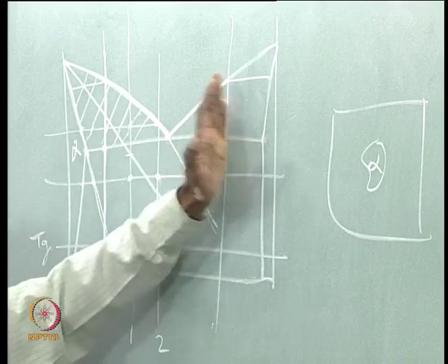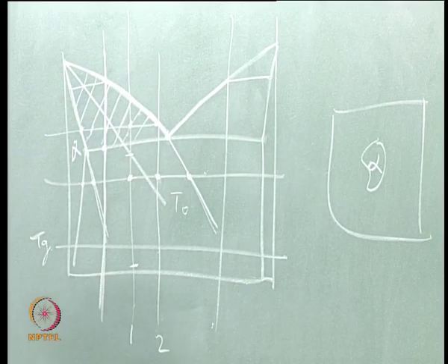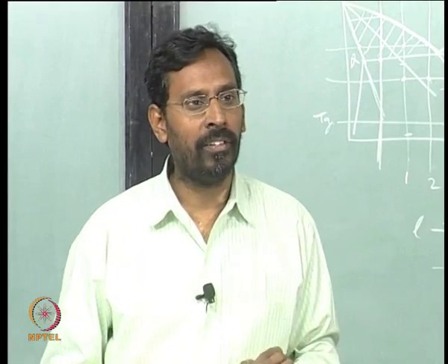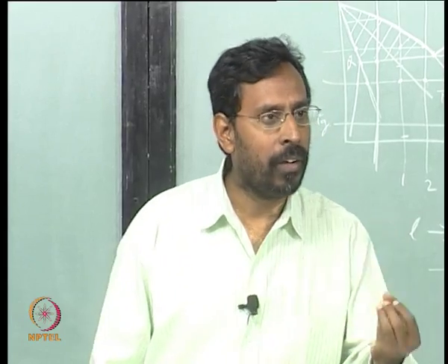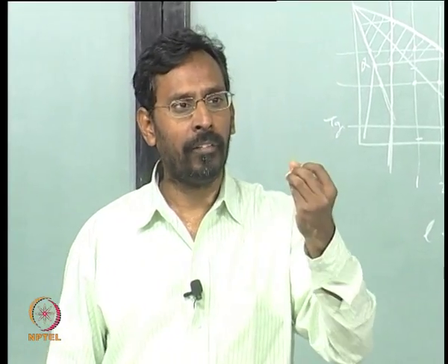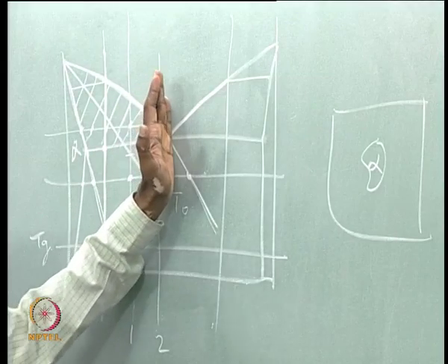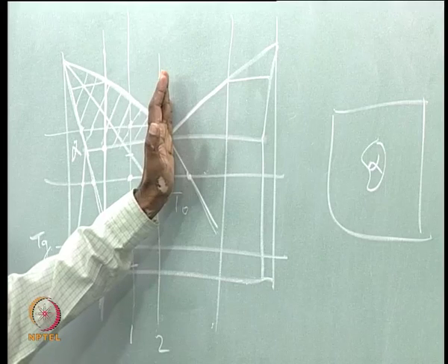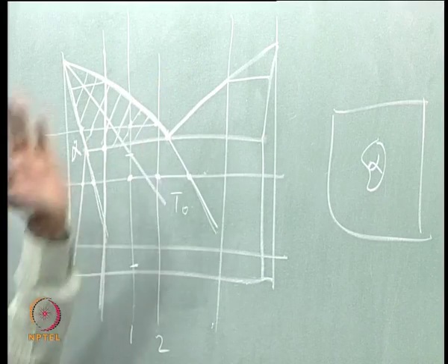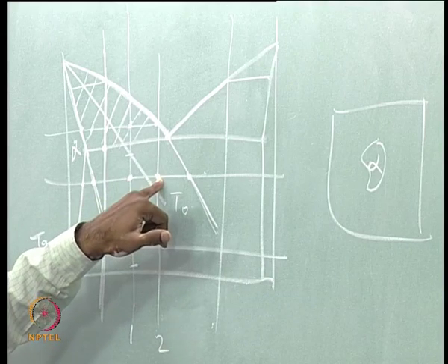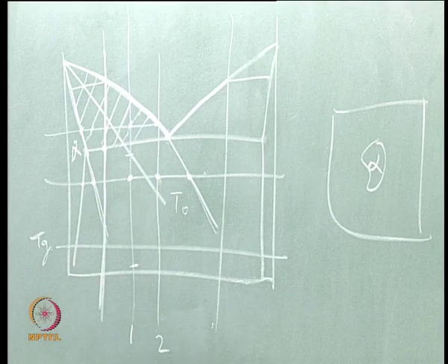So, whether you choose this alloy or any alloy within the eutectic domain, the eutectic reaction always happens from a liquid of a fixed composition, and that composition is the eutectic composition. So, that is the meaning of an invariant reaction. You cannot have any liquid giving you a eutectic reaction. So, because we are now talking about this liquid, yes, it is again the free energies.